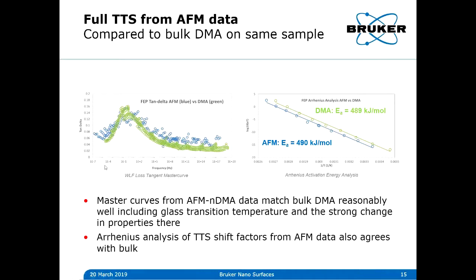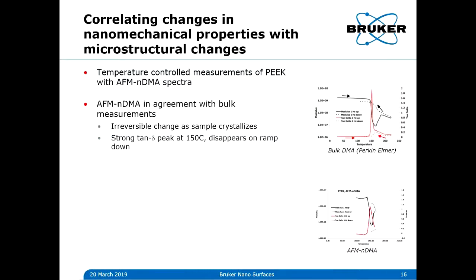And once you've created this master curve, notice that you now have the behavior of the material over more than 20 decades of frequency. So from extremely low frequencies that would be unbearable even for a graduate student to very high frequencies as well. If we compare the Arrhenius fit, the activation energies actually come out really close also for both the bulk and the AFM. So that's very encouraging.